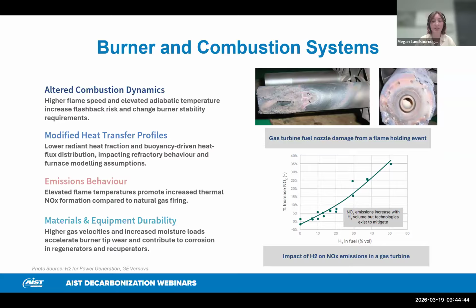As NOx and even CO formation are dependent on combustion temperature, higher hydrogen concentrations would increase these due to the higher flame temperature. And you can see this as an example on the graph that I have here on the right-hand side of the screen. And finally, hydrogen has higher gas velocities and increased moisture loads, accelerating burner tip wear and contributing to corrosion in regenerators and recuperators.